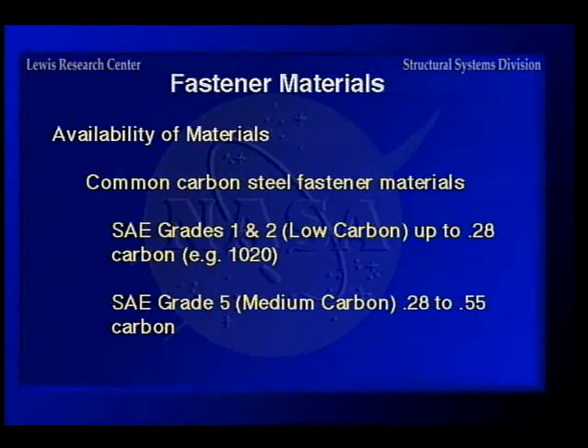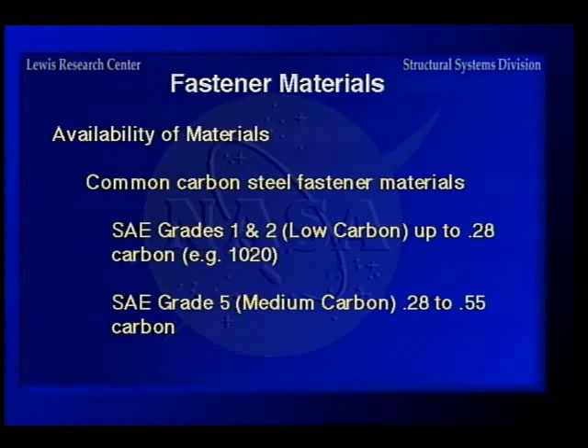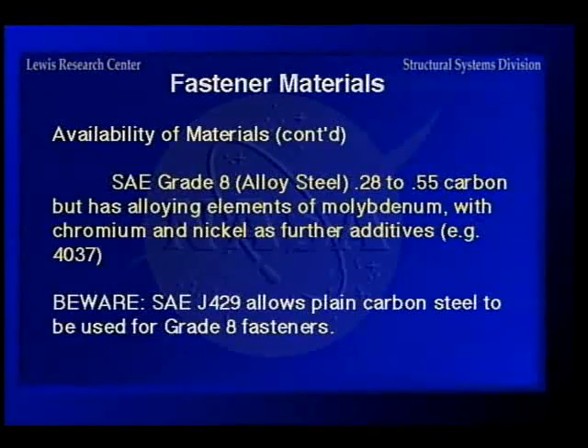And for heat treating, unless you add something like boron to the material, you need about 25 points of carbon really to get it to heat treat properly if you're going to heat treat a fastener. Now the grade 5s and grade 8s are in the 28 to 55 point carbon range so that they're heat treatable. And the 8s, of course, have other alloying elements in them in order that you can bring them up to the strength that you want. And 4037 is one of the common materials for grade 8.